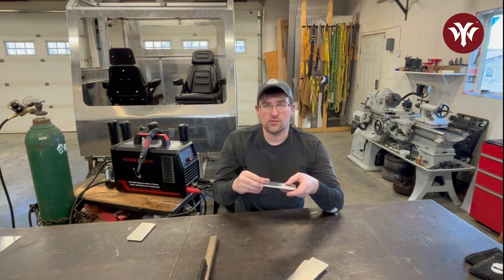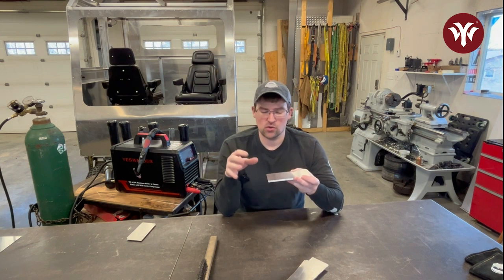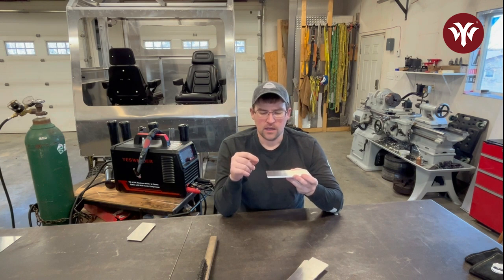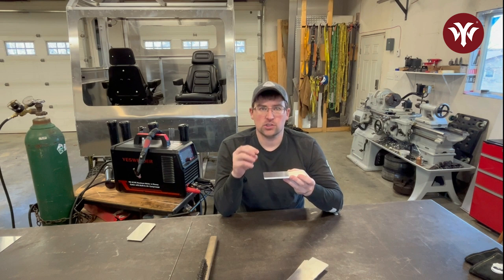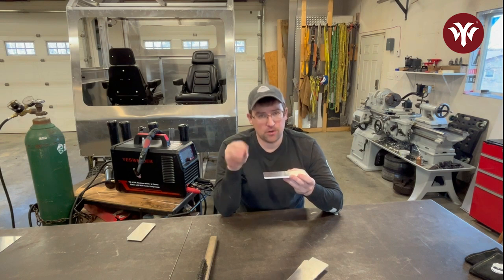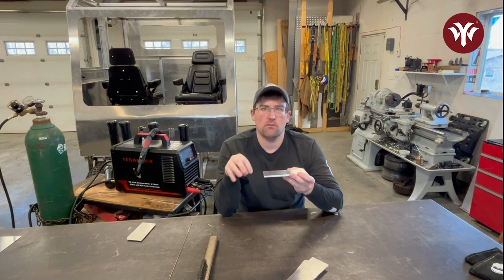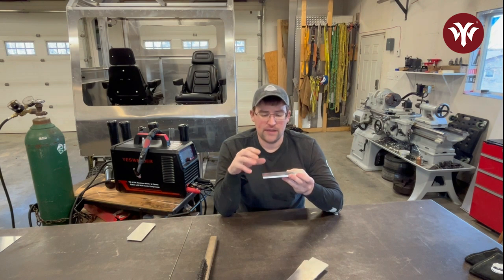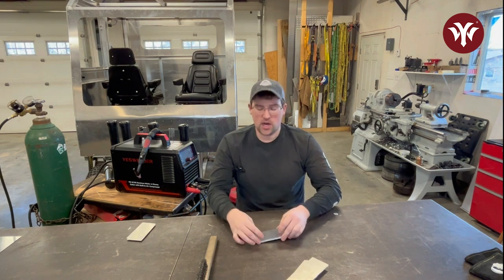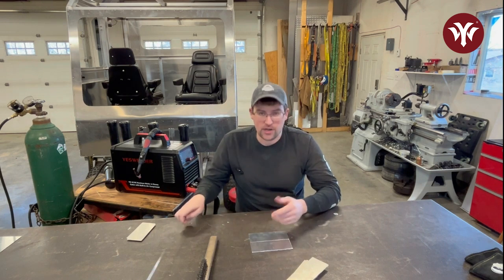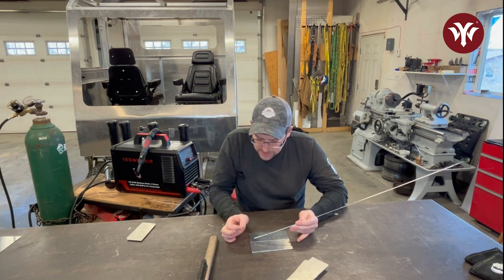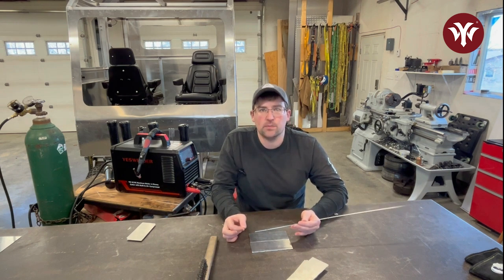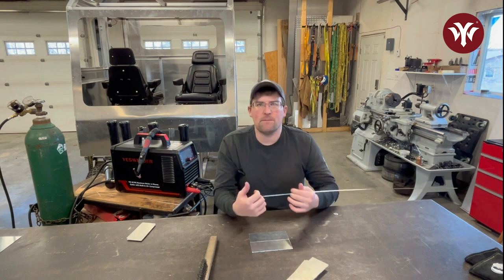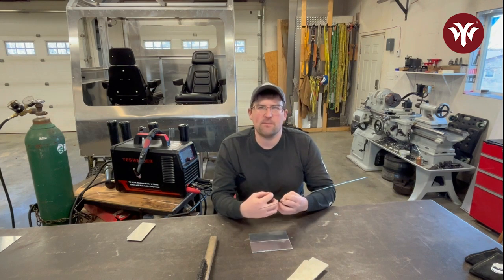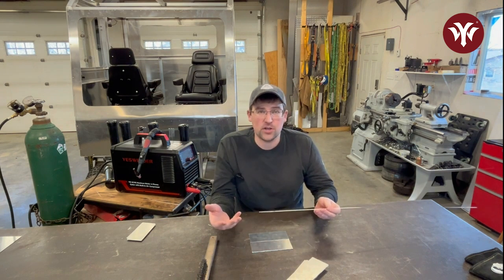If that oxide layer is really thick, which it just builds and builds over time, you're going to have to put a lot more current or heat into that part to get that puddle formed, because you have to burn through that oxide layer to get to the molten aluminum underneath. And that often causes issues, because as you're trying to get a butt joint or any kind of weld, as you're trying to get that puddle joined between the two parts, it kind of wants to repel itself. The oxide sort of separates it. It holds impurities in it.